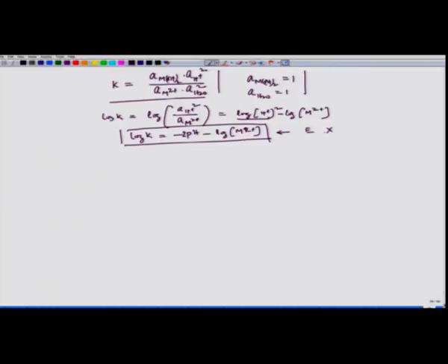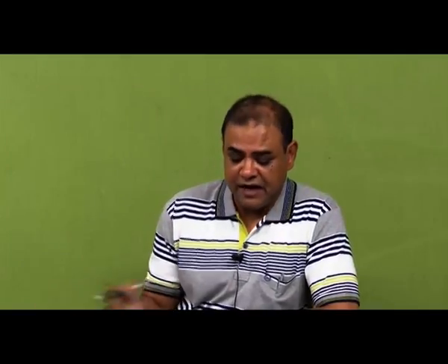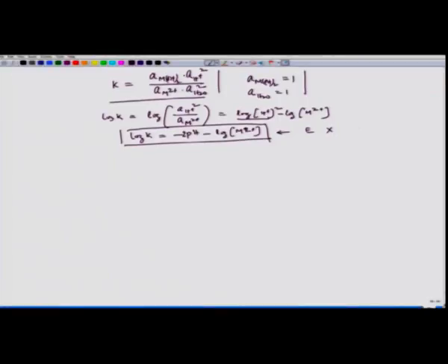So, the potential cannot decide this particular reaction, potential cannot tell me the stability of this particular reaction, because it does not involve any electron acceptance, or the system is not giving away electrons. So, no cathodic or anodic reactions are taking place in this entire reaction. So, it is pH dependent, a function of pH, because here we have pH, but it is not a function of potential. So, this is type 4. So, this equation becomes type 4.